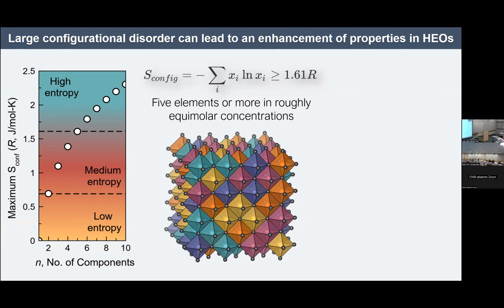In a high entropy material, the number of possible configurations is going to grow with the number of elements involved. So we can write down this formula, which is related to the Boltzmann entropy formula: we sum over i, the number of chemical species in the material, and look at the fraction, x subscript i, of that species on a specific lattice site. If that value exceeds 1.61 R, we define the material as being high entropy.